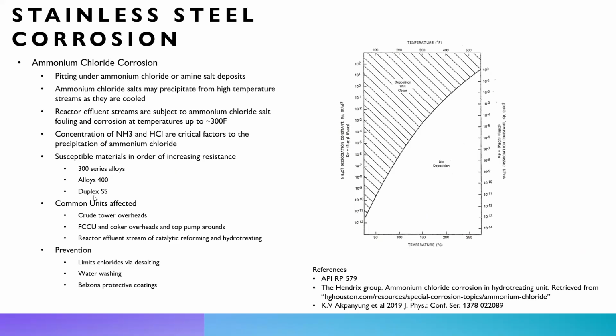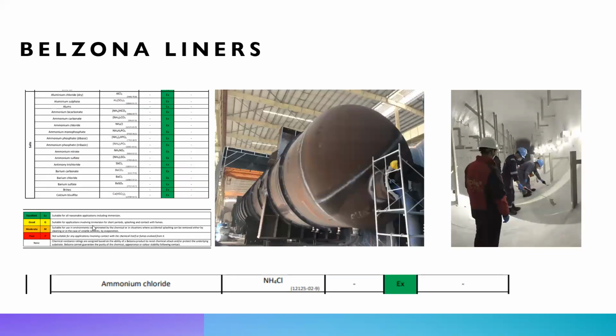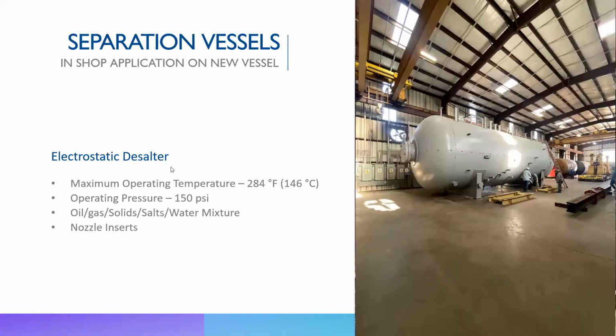Now, the other way we can help is if you go back to this slide, one of the ways the industry deals with ammonium chloride corrosion is to have a desalting service before you go into your crude tower. So typically refineries will have a desalter before they go into their distillation process. Now these desalters, typically what we've seen, are made of carbon steel, and most of the time they are lined with an internal liner. So we do a lot of liners for desalters.